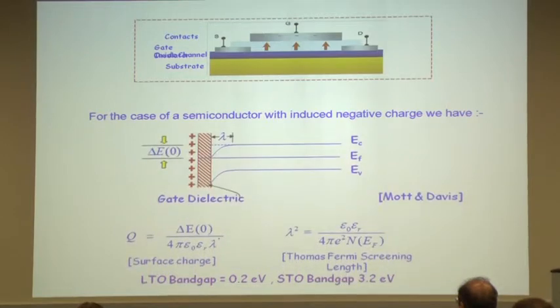And how well the gating is going to work depends on this parameter, the so-called Thomas Fermi screening length. So if I have the gate dielectric here, I apply a positive charge. This is my semiconductor, which I'm trying to modify. There will be a band bending at the interface, and the length scale over which this band bending is effective is decided by the so-called Thomas Fermi screening length. It depends on the dielectric function of the semiconductor and the gate material, and also on the density of states of the semiconductor at the Fermi energy.